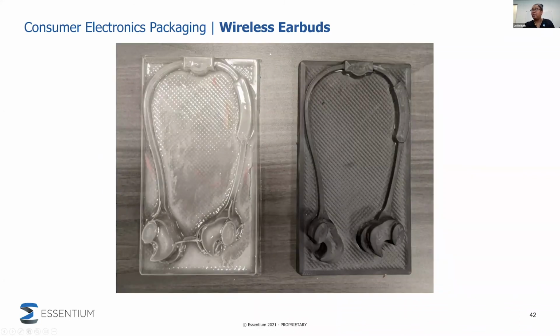You can see here, then I trimmed the excess, and we have the resulting mold here. And like I mentioned before, some defects that can come from having too thin walls include the perforations or the internal infill showing up in the final result. So if that's an aesthetic that you're looking for, it might even be better to add complexity to your 3D model while still maintaining thicker layer heights. You could 3D model textures onto your mold and then add additional perimeters to your mold so they don't collapse after sustained heat.